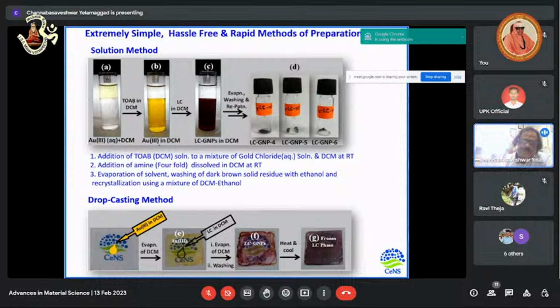I feel that even this kind of chemistry can be done at the university, just in BSc laboratories or MSc laboratories. Look at what we have done. We have taken dichloromethane, DCM, and an aqueous solution, Au3+ ions put in water. So you can see 2 layers separated. Dichloromethane is here, and the water containing Au3+ ions is here. The moment you add a phase transfer catalyst, the Au3+ ions move to the organic layer, and now we take our organic molecule in DCM and add it dropwise.